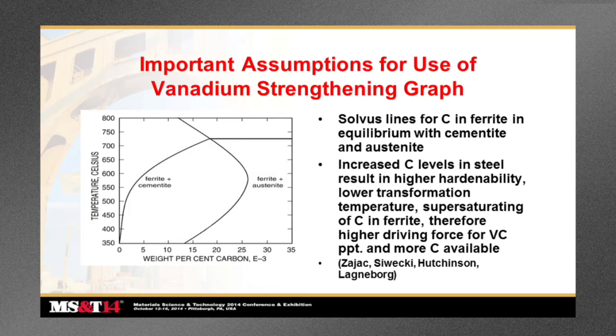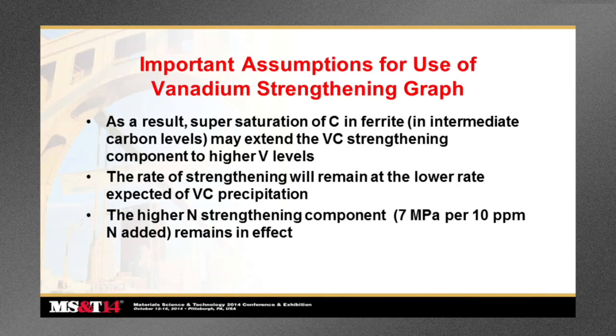So you get a ferrite-pearlite kind of structure, but with higher carbon levels, you can have higher hardenability, therefore lower transformation temperatures, potential supersaturation of carbon in the ferrite, and therefore a higher driving force for vanadium carbide precipitation and more carbon being available. As a result of this supersaturation of carbon in the ferrite, you may extend the vanadium carbide strengthening component to higher vanadium levels. So the rate of strengthening, though, will still remain the same as shown in that curve, and the higher nitrogen strengthening component, the 7 megapascals that we quote, is still relevant and is still appropriate for these intermediate carbon levels. The differential increase that you can get with nitrogen, as long as it's substoichiometric to the VN ratio, is always consistent near the 7 megapascals if appropriately processed.